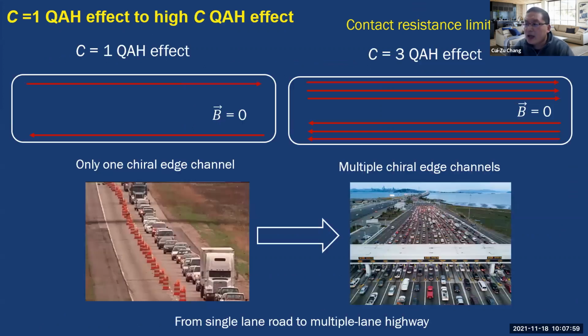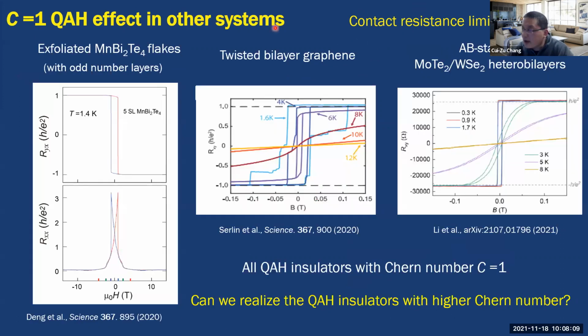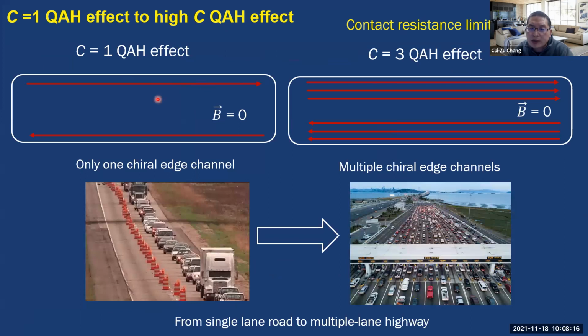Before moving on, let's compare the C equals 1 quantum anomalous Hall effect and the high Chern number quantum anomalous Hall effect. If we want to reduce the contact resistance, we need to increase C here. In C equals 1 quantum anomalous Hall, there is only one chiral edge channel. When the electron is traveling in this chiral edge channel, just like cars going from the highway to the downtown, it usually takes a lot of time. However, in high Chern number quantum anomalous Hall insulators, there are several chiral edge channels. It will greatly reduce the time from the highway to the downtown of the city.